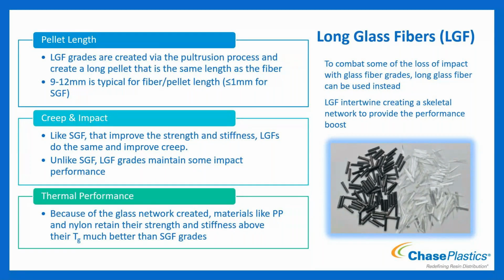Glass transition temperature—we know that when we hit that, our materials start to be able to move. It's where molecular movement is allowed for that material. As you get close to it, if you're looking at a modulus versus temperature graph, you'll see a drop in stiffness as it gets close to that temperature. Because of the skeletal network with long glass fiber, it actually maintains that stiffness and strength a little bit better, and a little bit past that TG, than you get with short glass fiber.